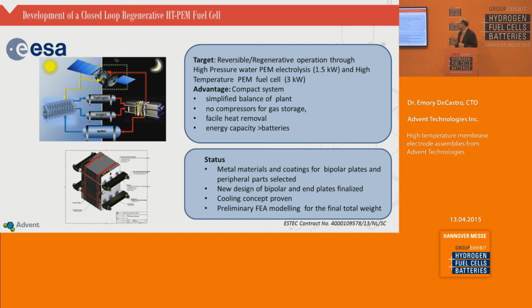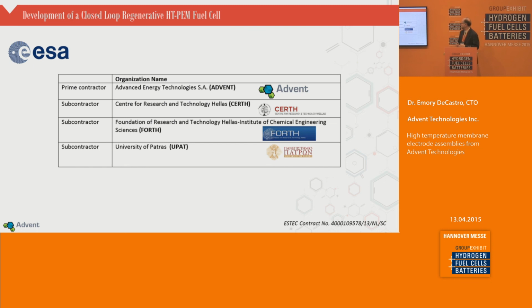One key, though, for our research group, is coming up with a lightweight, small-volume cell, which means going to metal bipolar plates, certainly a challenge at these temperatures with phosphoric acid. But we've identified some potential candidates, and those are being tested today. There's also some new design of bipolar plates, and we've actually shown the cooling concept that we propose to work at the bench scale. And so right now we're going through our preliminary modeling to show the final total weight and power. So that's an ongoing program. And again, our partners here are limited to Greece, but certainly within the technical centers of Greece for this.